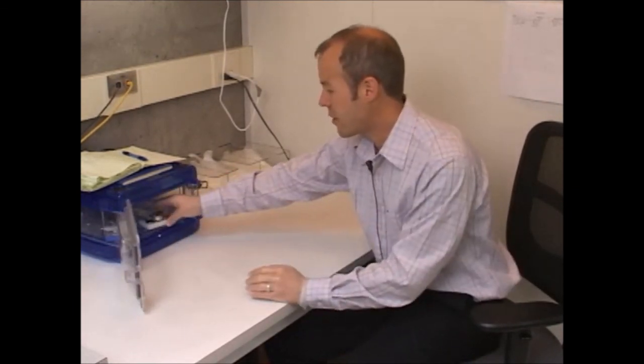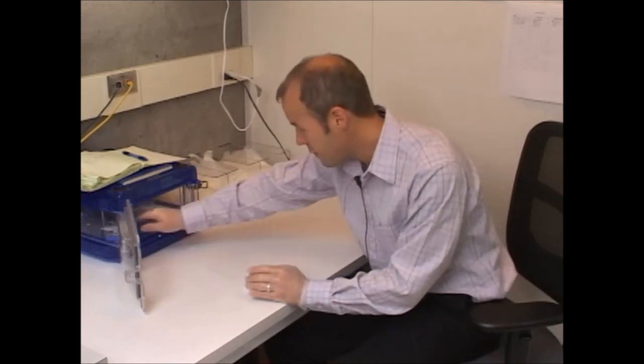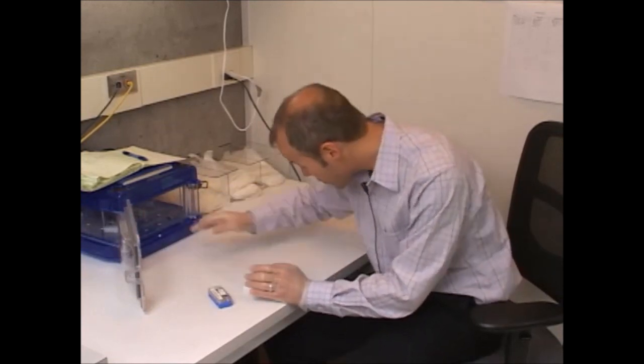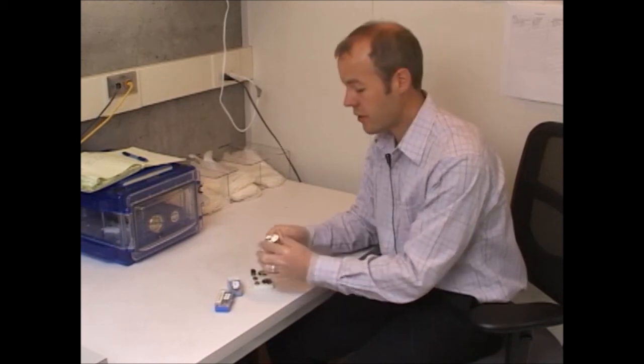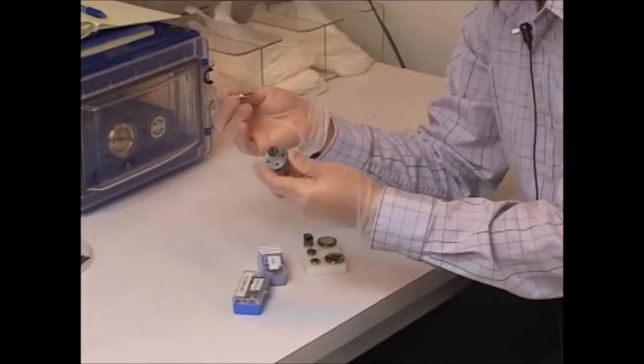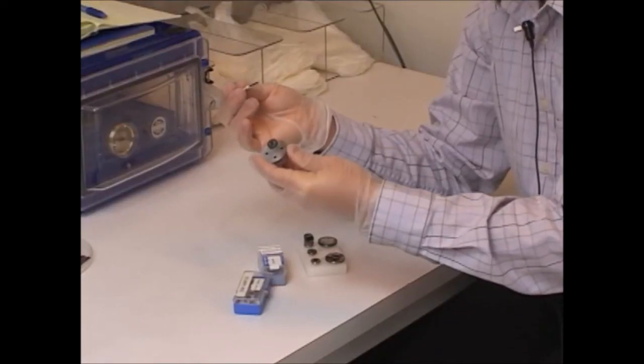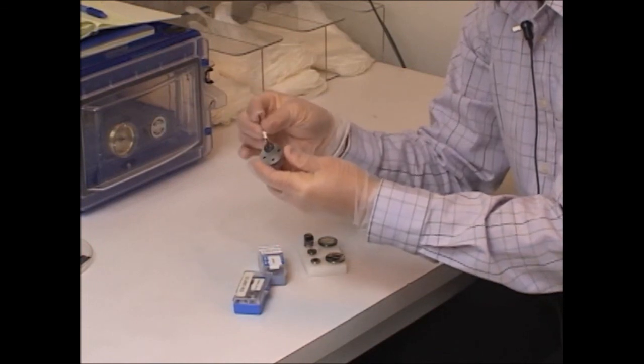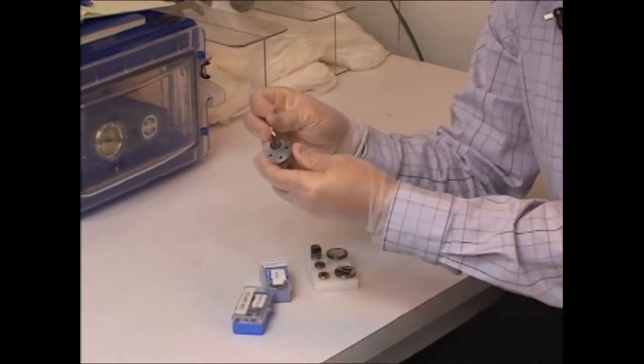So out of the desiccator box, I'm just going to take a few standard samples that I keep for training purposes. The inside of the chamber only has room for one pin mount stub, one sample. So we use this 4-stub adapter in order to expand the stage so that you can look at up to 4 small samples in one sitting without having to vent the chamber to atmosphere and reload it. Each position on this 4-stub holder has a set screw in the side to secure the sample. It needs to be loosened first with an Allen key before you can remove the stub.